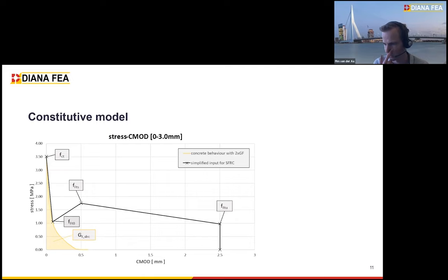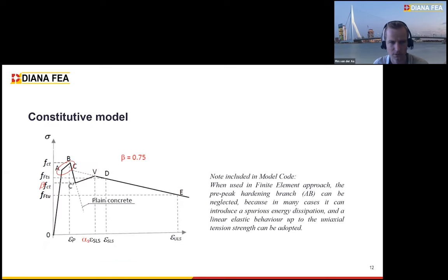If we then continue, the full stress CMOD diagram, or the stress strain diagram related to it, will look something like this. We proposed to introduce some sort of drop point, FT0. The height of that point should be more or less related to the type of fiber you're going to use. So what was now proposed for the constitutive model in the model code? You can see that C prime is now introduced. You don't have to use it, but you can use it, for example, for these hooked end fibers.